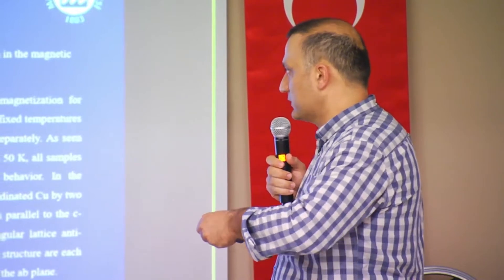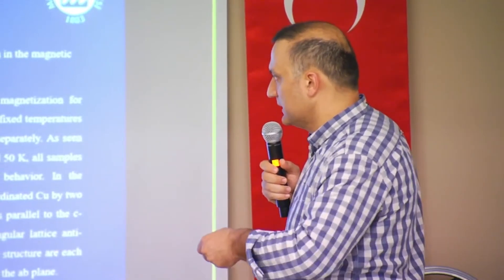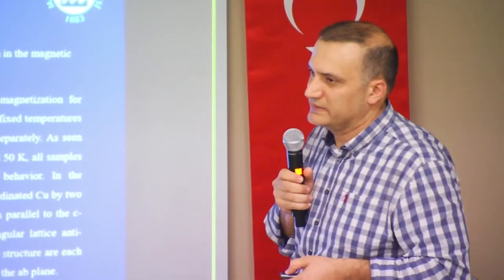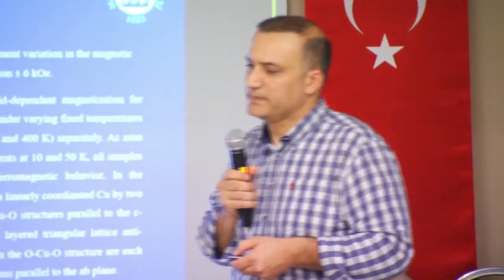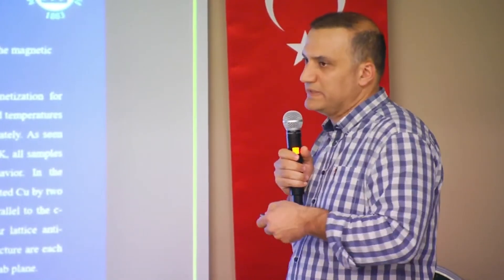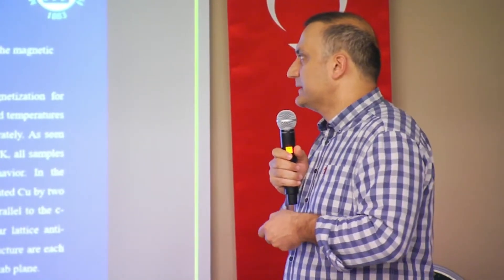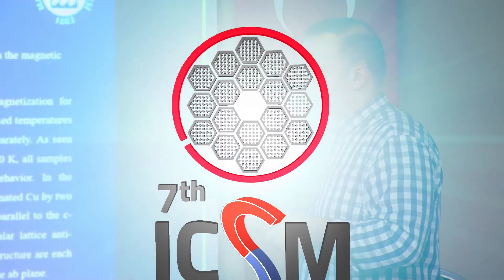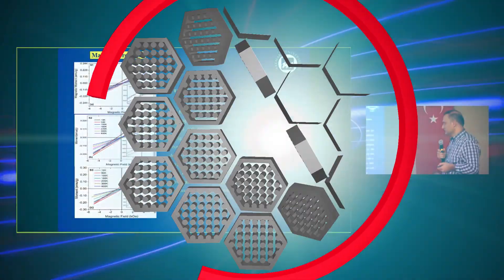The physical meaning: if we see the moving to the negative part without saturation, this means it's antiferromagnetic. There's no saturation here, no saturation here, and this part we have a move to the negative part, which means it's antiferromagnetic. If we have a saturation here, it is ferromagnetic. We can classify like this. This is not a kind of actual hysteresis loop. It's a kind of antiferromagnetic loop. Due to no saturation and the system moving to the left side, we get this behavior.